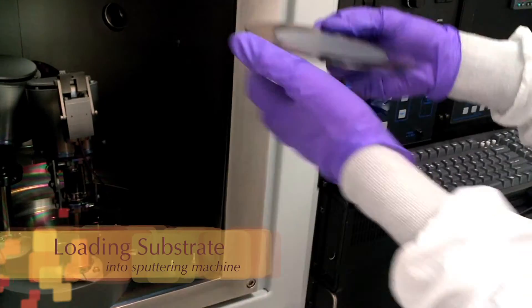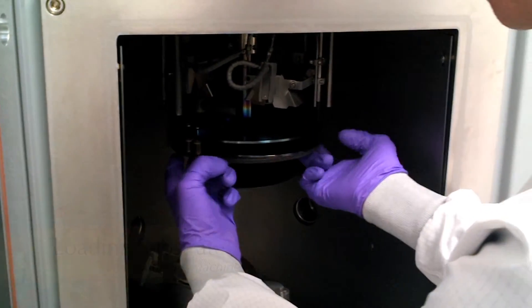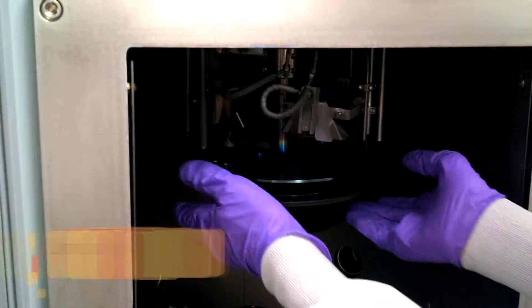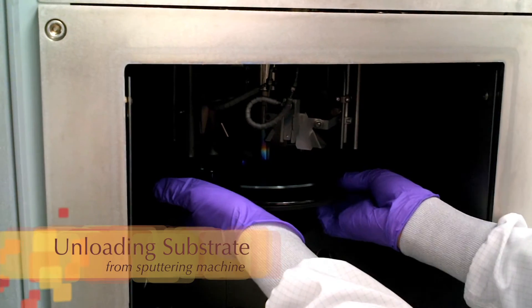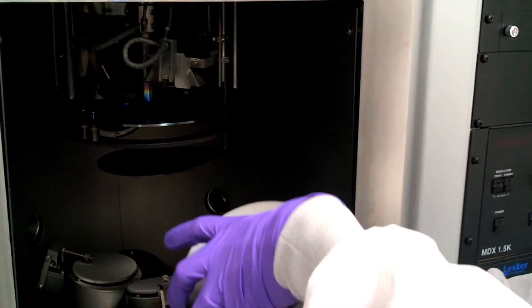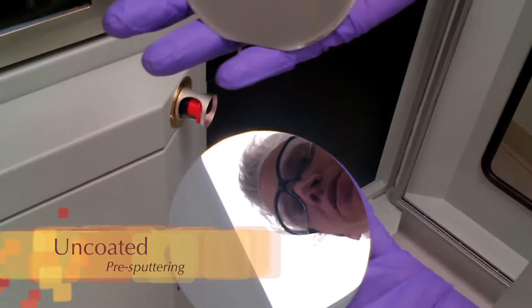If a final metallic MEMS device is desired, a thin titanium seed layer is applied onto the substrate with a sputtering process. The titanium layer is then oxidized. This is done to provide a better surface for adhesion of the polymer resist later. This step is skipped if the final device is a polymer microstructure.